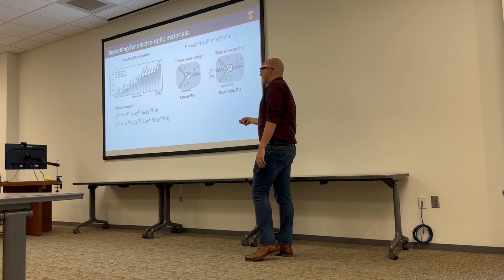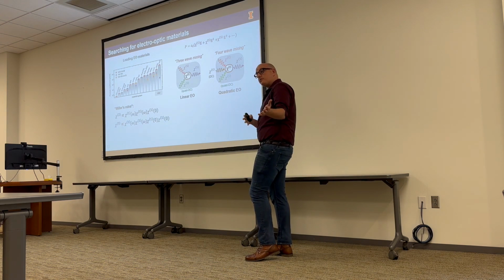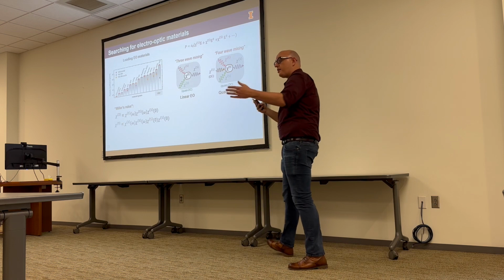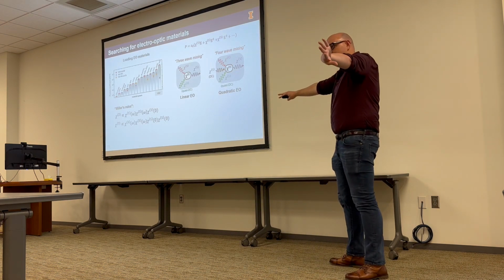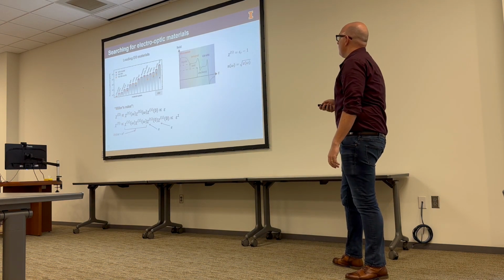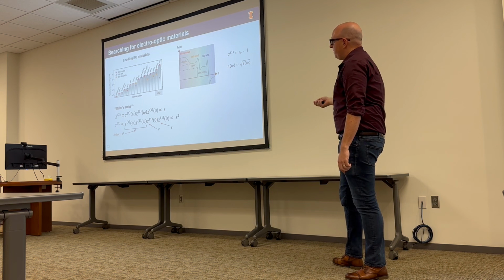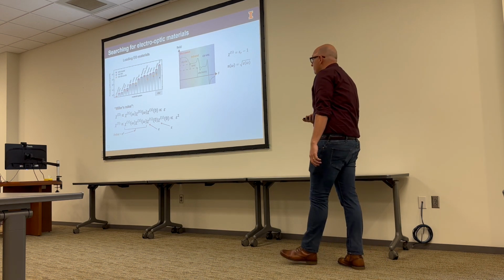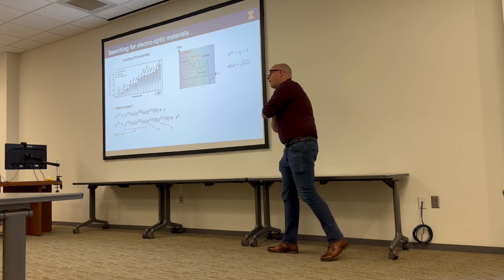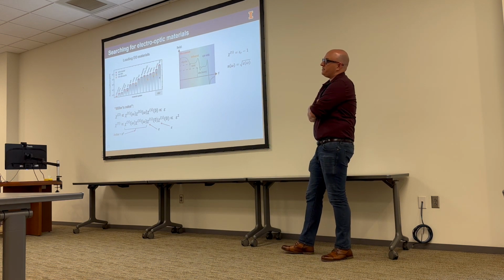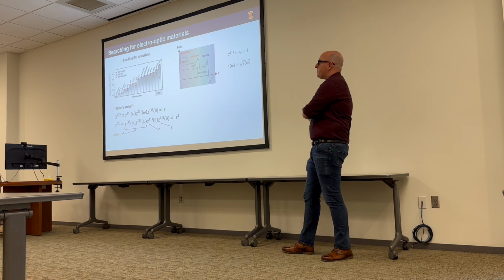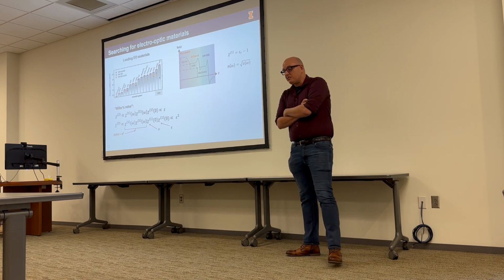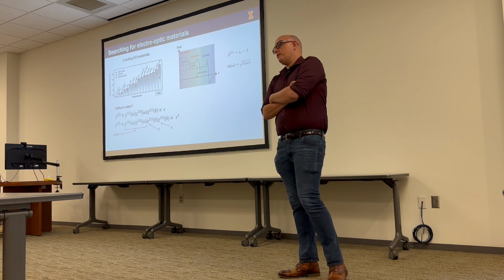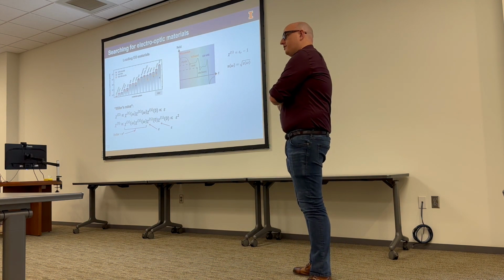For electro-optics, some of these susceptibilities are high frequencies, some of them are low frequencies, right? It's microwaves and optics, 30,000 difference in energy between those. And that's great because materials have drastically different susceptibilities in different frequency ranges. So basically every optical material that you know has an index that's somewhere between like 1 and 5 maybe. But the dielectric constant, the sort of DC susceptibility of materials, can be like 0 or like 100,000.